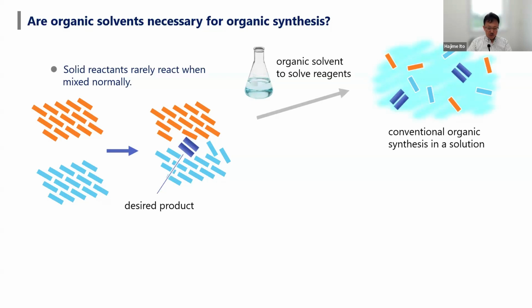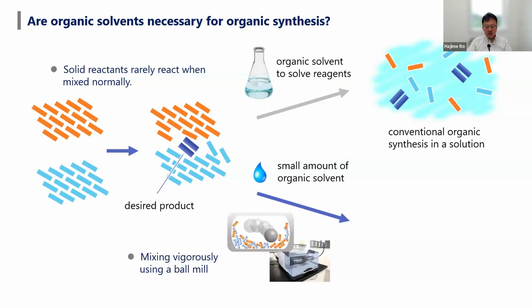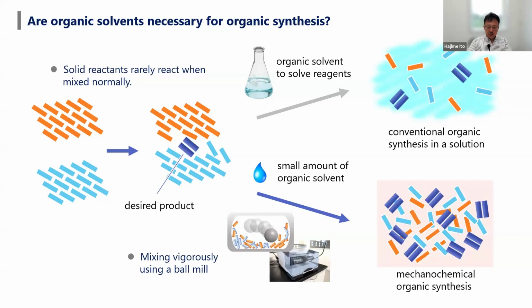Instead of just mixing molecular organic crystals, we organic chemists use a large amount of organic solvent to dissolve these compounds so they can react freely in solution. But recently, some mechanochemistry researchers found that by using a ball milling machine, we can conduct organic reactions with solid materials in the presence of a small amount of organic solvent, or in the absence of organic solvent.